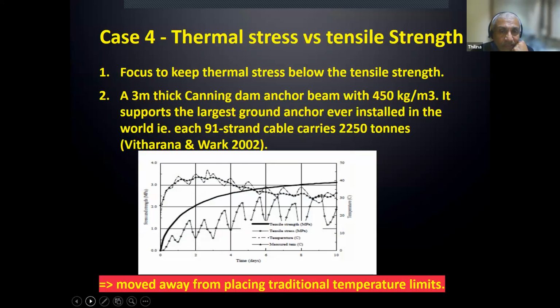Thermal stresses versus tensile strength. As I said, this is done for Canning Dam in Western Australia. It's a gravity dam. It had alkali aggregate reaction, and I think I did a presentation about 6 months ago. We put in 91 strand cables drilled through the dam and 130 meters into the foundation. Each cable had 91 strands, and each cable carried 2,250 tons. I think that's the weight of a US largest aircraft carrier. There we couldn't take any chances on the anchor block, because if it cracks, there's no guarantee that the anchorage would be okay. So we did a very, very comprehensive model.